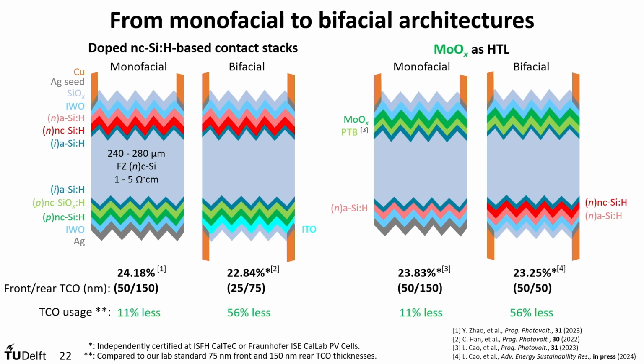I would also like to mention that we lose some efficiency in the case of bifacial, because here we are measuring the devices without any back reflector. So in open field, this number would, of course, be higher. But the standard is that we need to measure with a non-reflective chuck. What I want to put the accent on is that despite having lost some efficiency in STC conditions, we can use much lower TCO, for example, and in this respect already minimize, in some ways, the use of indium in this technology.